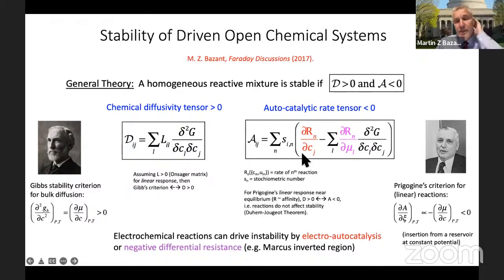But much more interesting and more novel is a generalization of Prigogine's condition for linear reaction models to a general nonlinear situation, including these electrochemistry models, where what I call the autocatalytic rate tensor has to be negative. So essentially the rate has to be slowing down as it progresses to be stable, otherwise it's unstable. And it's very common to see this sort of strong nonlinearity in electrochemical reaction rates.